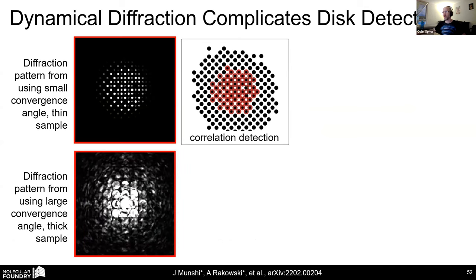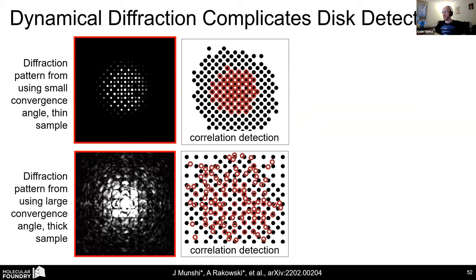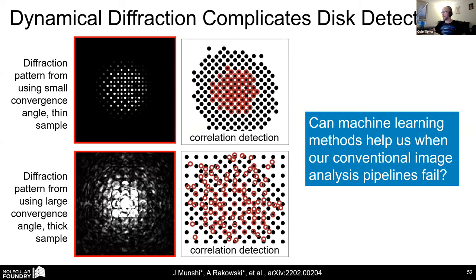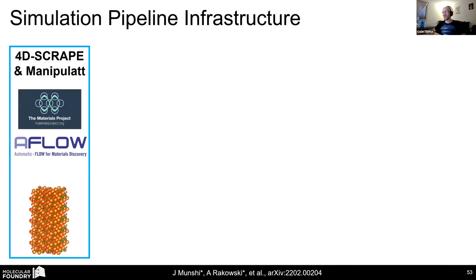But what if you don't know your material ahead of time and your lattice parameter is a lot smaller, you have overlapping disks, you have multiple scattering inside the disks, you get really complicated diffraction patterns. If you use the conventional methods, they completely fail when you're trying to analyze diffraction patterns like this. So what my group wanted to know is, could machine learning methods help us overcome this barrier? We take the Materials Project and AFLOWLIB databases, and we pull in every crystal structure known.